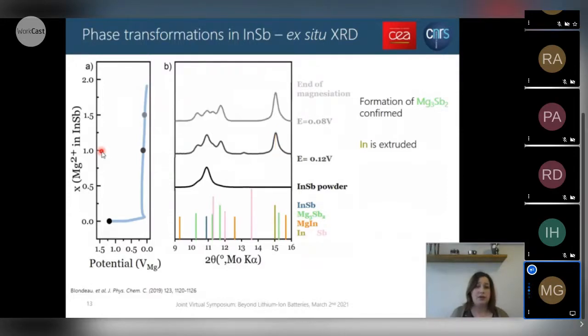If we go further into the magnesiation, up to 1.5 Mg2+, we still see formation of Mg3Sb2 and metallic indium. Finally, when we go till the end of the magnesiation, interestingly, we can see some small peaks at 9, 12, and close to 16 degrees that may correspond to the MgIn phase. However, one thing I want to highlight here is this was the only time that we've seen those peaks, and when we reproduce the data, these tiny peaks were not present. We will see it just after. So that means that at the end of the magnesiation, we clearly see the formation of Mg3Sb2, but we see MgIn either in a really poorly crystalline state or even in an amorphous state.